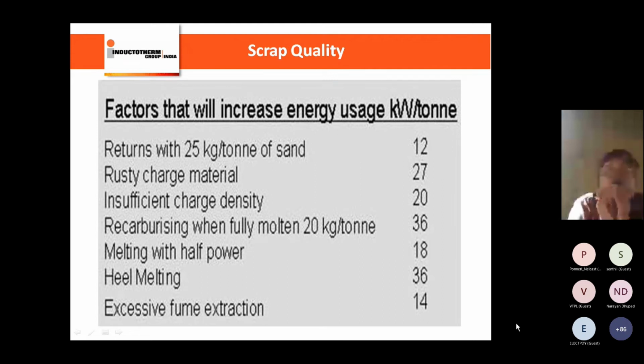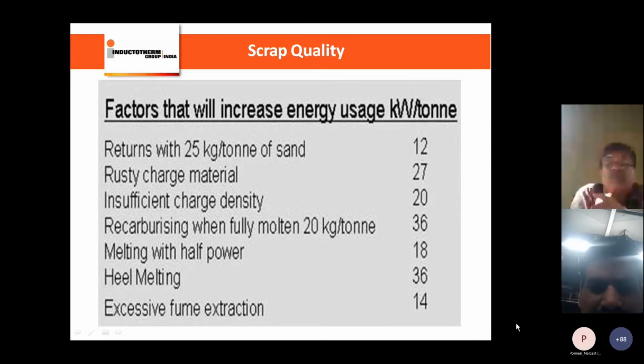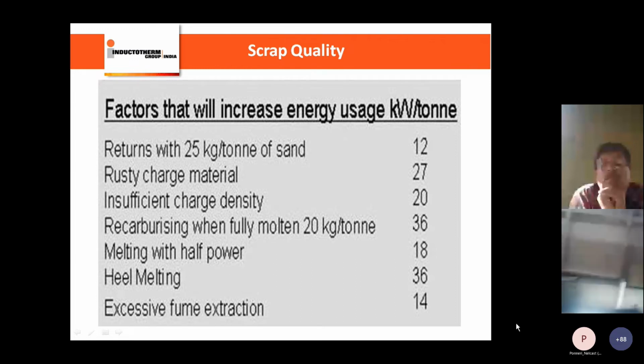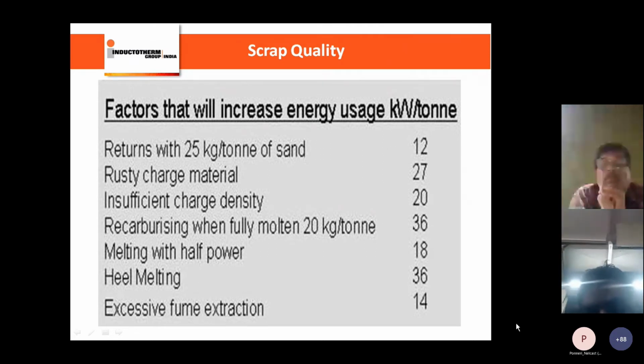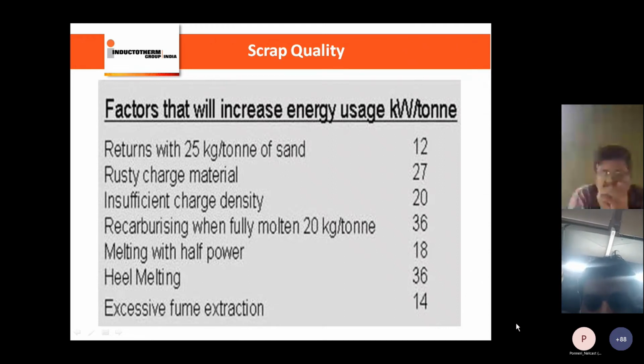There are foundries who shot blast their returns when feeding them back into the furnace, and they don't allow any rust or scrap into the furnace. But each and every uncleaned, rusted, sandy boring, non-metallic, and inorganic material contributes to increased consumption. To an extent, excessive fume extraction also does, where you have the canopy or side draft fume extraction systems, and sometimes even heel melting, so melting with lower powers. So various factors contribute to higher power consumption, which we need to minimize so that one can achieve utmost efficiency. The second factor, after energy efficiency, is the scrap efficiency.